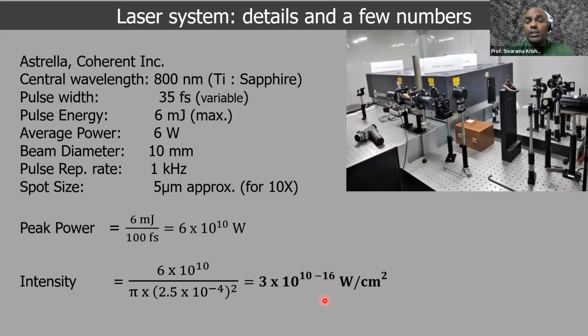Now, what's so special about these numbers? 10 to the 16 watts per square centimeter is typically the electric field experienced by an electron which is bound in an atom, or in a crude cartoon model, which goes around the nucleus in an atom. It is bound by the electric field of the nucleus, right? This is something we learned in school. Now, the applied external electric field from this laser can challenge the native Coulomb potential, right? So in that sense, the interaction is very, very nonlinear between the laser and the material here, which actually underlies these tremendous advantages that I spoke to you about. Plasma formation, and hence a different way of ablation, which leads to a very athermal and precise process. Okay, so these numbers in one sense are quite important to be maintained in order to get the best results.